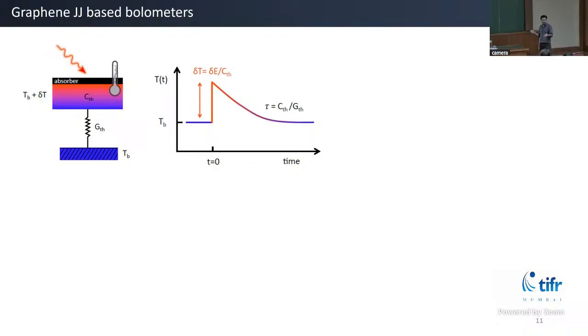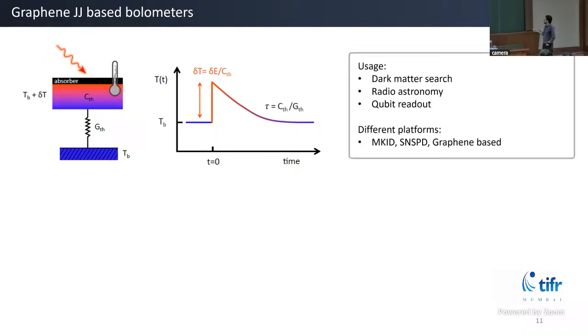That's where graphene is very helpful. Graphene has a very low specific heat. So if you dump a little bit of energy, that will give a high temperature rise in your devices. Another parameter is how fast it resets back to the cool state, and that is determined again by the specific heat and the thermal conductance to the bath. As I mentioned, these bolometers are used in many fields, for example dark matter search, radio astronomy, qubit readouts, and there have been different platforms using MKIDs, SNSPD, and other material platforms.